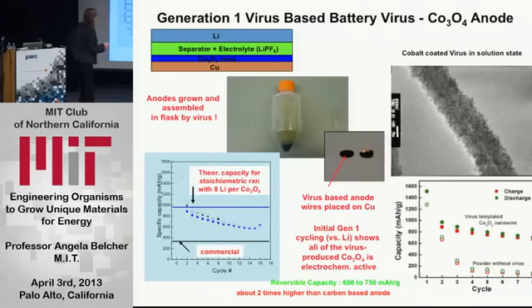And so then we're going to test this as a battery electrode material. We put it on copper. We had a separator and the electrolyte. We used lithium as our counter electrode to test it. And what we're going to measure is specific capacity and cycle. And so I always say this is the first data that we did, but it's actually the first data I saw because I think my students don't show me all the things that don't work at first.